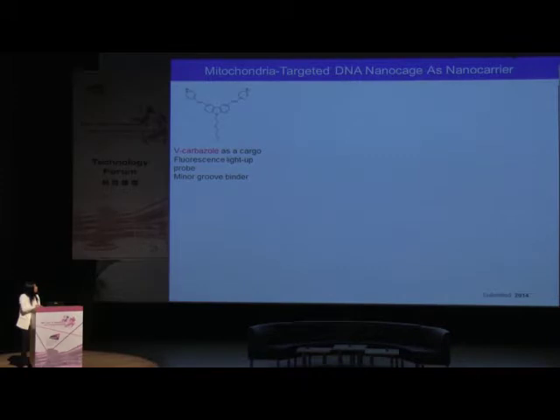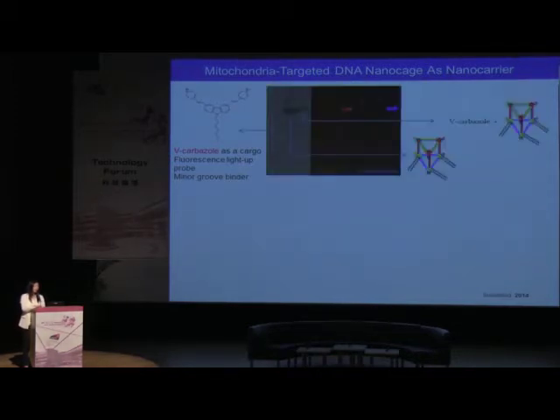So to demonstrate that this DNA nanocage structure can be used as a nanocarrier, we took a V-carbazole molecule as a cargo, which has been proven as a fluorescent-like probe and also a minor groove binder for duplex DNA. From the gel analysis, we can see that this V-carbazole cargo was successfully loaded onto the cages, with a lower mobility on the gel as compared to the control. They also show overlapping of the fluorescence from the cargo and the cage.